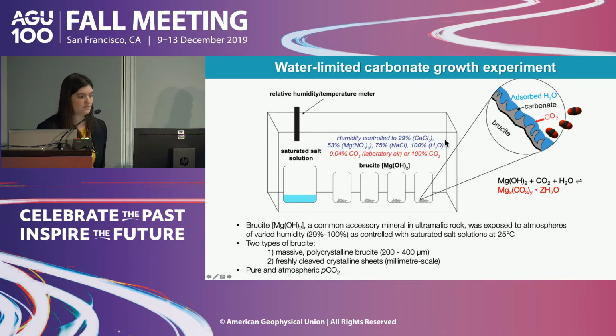And so it's known if you expose a mineral surface to a humid air, you will develop an adsorbed water film at its surface, the thickness of which depends in part on the relative humidity. And that adsorbed water film may be enough to facilitate reactions. And so what we did is we took our mineral brucite again, we exposed it to different levels of humidity, which we controlled using saturated salt solutions, ranging from 29 to 100% humidity. And we exposed it to either lab air or 100% CO2 and tracked the reaction over time.